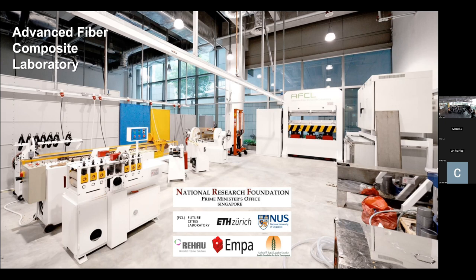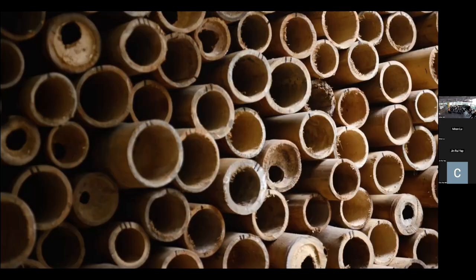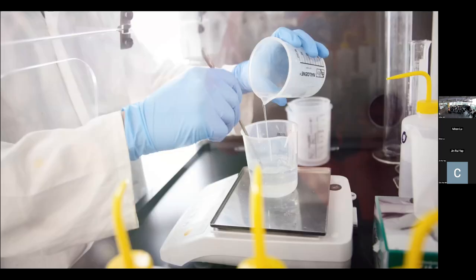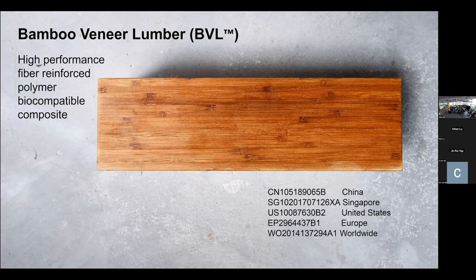Therefore, we started to explore various methods of how to extract the bamboo fibers, and how to make the binders more sustainable. So we started to collaborate with some German and Swiss polymer companies. We focused on fiber extraction in our lab. The companies helped us with the development of a sustainable binder solution. And that's where we developed these composite materials out of bamboo. What we had here was 90% bamboo fibers that we managed to extract without damaging the fibers. And we managed also to patent it in several countries, several regions.